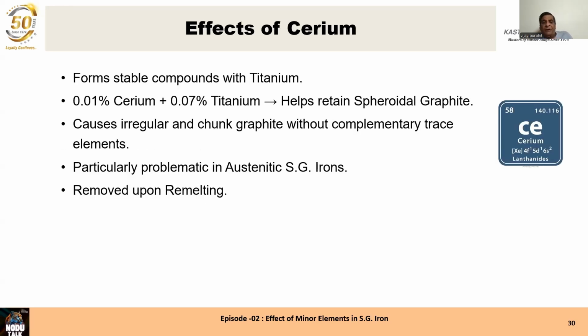Effects of cerium. We have seen that cerium forms stable compounds with titanium. 0.01% cerium and 0.07% titanium helps retain spheroidal graphite. Cerium causes irregular and chunky graphite without complementary trace elements. If the trace elements are absent, then cerium causes chunky graphite. So cerium is both a friend and an enemy. If bad elements are absent, then cerium should not be used, otherwise it will form chunky graphite.